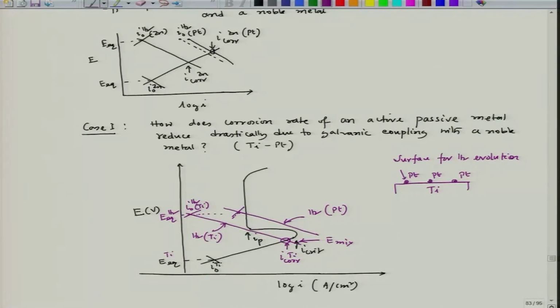So, the mixed potential now falls on this particular section. At this point, the anodic polarization curve for titanium is being cut in the passive region. So the corrosion rate of titanium will be this, which is I corr titanium, when it is galvanically connected to platinum. And of course, when we have these platinum-enriched zones on the surface, initially the titanium has to go through this track, first reaching the maximum I critical region, and then finally falling to this, because this is my mixed potential.